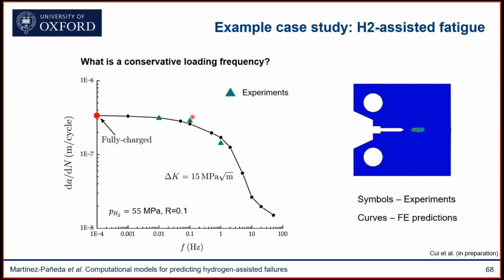And what we can show is actually that we see the expected trend. So we go between two plateaus, limiting cases: when we load so fast that there's no time for the hydrogen to distribute within the material, and when we load so slow that hydrogen has all the time that it needs to achieve the steady state and uniformly distribute itself within the material. And what we can see is that our predictions are in good agreement with experiments. So that's good news, I think, for both of us.